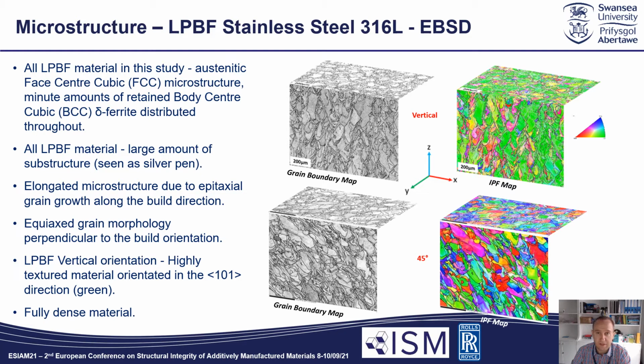And then in both orientations, an elongated grain structure is also apparent on the face parallel to the build direction, resulting from the epitaxial grain growth during manufacture, with an equiaxed grain morphology, as expected, seen on the perpendicular face. The vertical build can be seen to be highly textured in the 101 direction, and as a result of the hipping procedure, the material is now fully dense, with no evidence of porosity seen in either material.